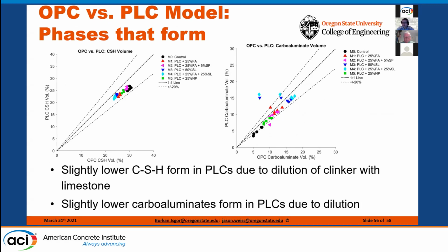Now, one of the other things that I will mention here is we're going to compare the aluminates and we're going to compare the CSH from an OPC system to a PLC system. What was initially a little bit surprising to me is we see a slightly lower amount of CSH when we have PLC in the system compared to OPC. But this is when you look at it as the overall system. The real takeaway from this is we would expect to have slightly lower CSH. In fact, we'd have 10% or 12% lower CSH if we just base this on dilution. But we don't have 10% lower, we have more like a 5% lower value. This is telling us that we're getting about 5% more of the clinker reacting to form CSH. And we have a similar story with our carboaluminates.